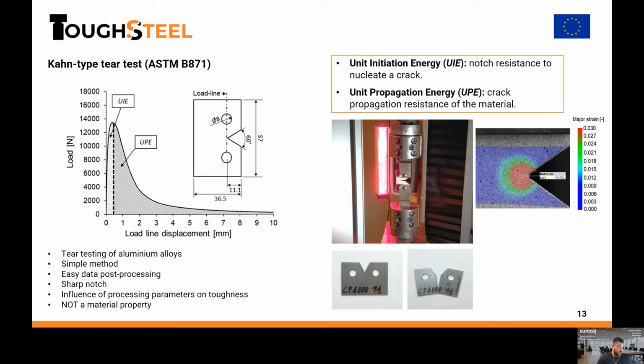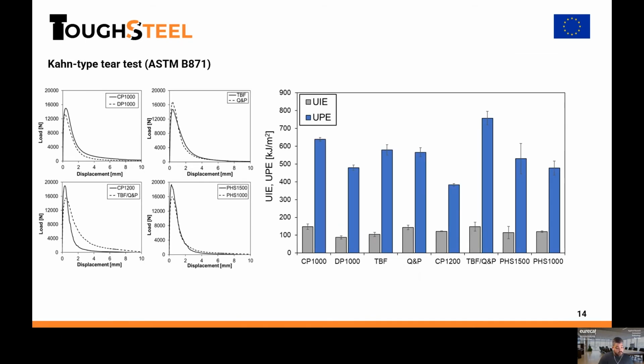As I said, this is a very simple method and it has been very interesting for a fast, let's say, screening of materials. However, it's important to take into consideration that it's not a material property. So, as the standard suggests, it must not be considered a fracture toughness value itself, but let's say a toughness index. Of course, the geometry and the test setup are quite simple, and it can also be combined with digital image correlation, which is also very interesting to obtain different parameters. However, we will see that we must be careful when considering the results of the different testing methodologies.